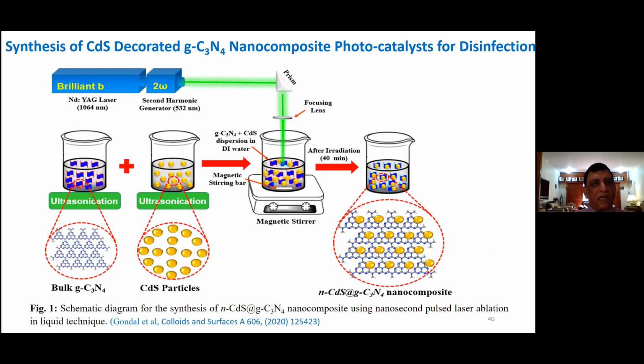For the preparation here we basically use wet chemistry as well as lasers. First we make bulk graphitic carbon nitride particles from melamine, and CdS particles. Then we mix them on a magnetic stirrer and we break them with the second harmonic, which is a 532 nanometer laser.